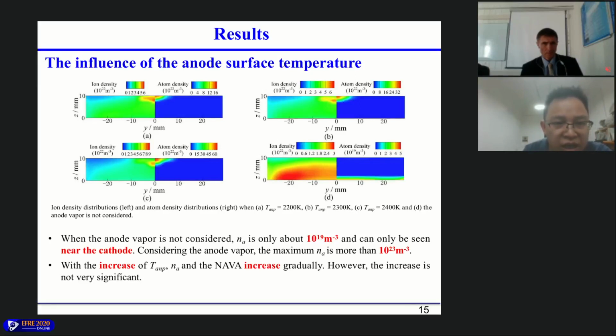This is ion density. This is atom density. When the anode vapor is not considered, we can see in these figures that atom density is only about 10 to the 19 per cubic meter, and can only be seen near the cathode side. But considering the anode vapor, the maximum atom density is more than 10 to the 23 per cubic meter. And with the increase of the anode temperature, the atom density increases gradually. However, the increase is not very significant.